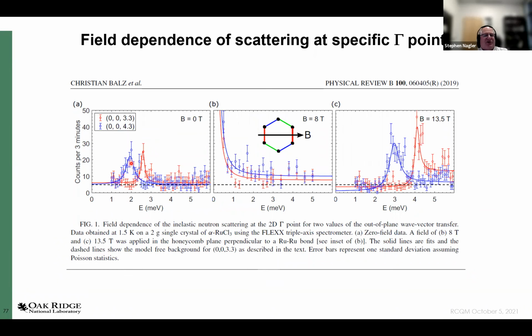What you see at 0 field are a couple of sharp spin wave peaks, and here we do see a continuum. And when you go into what we think is a disordered phase, these sharp peaks are very hard to see or invisible with neutron scattering. The continuum is stronger. And eventually we get to a state where we have sharp peaks at a lower threshold and a fairly strong continuum above that.